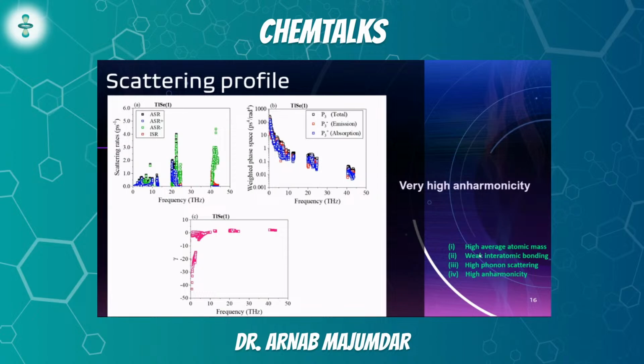Especially if you look at the graph at the bottom, the gamma, that actually represents the Gruneisen parameter, which itself measures the anharmonicity. And you can see that at lower frequencies in the acoustic region and for the first two optical modes, the Gruneisen parameter indeed is extremely high. When I say high, I mean magnitude-wise high. So it could be negative, it's negative 40, but the magnitude is quite high. Whereas for the higher frequencies, this value hovers around 0. That means for the higher frequencies, this material is not very anharmonic. It's only for the lower frequencies that it's very anharmonic. And values like -40 or -45 are actually very high numbers for a Gruneisen parameter.